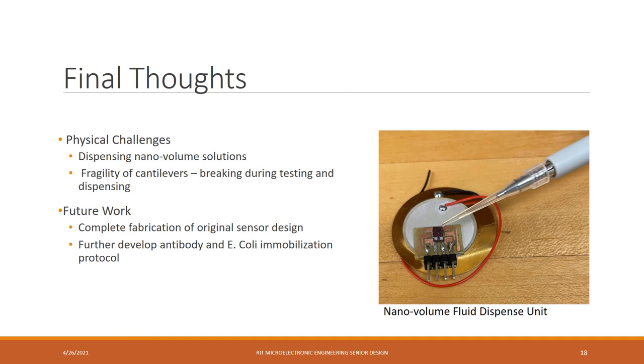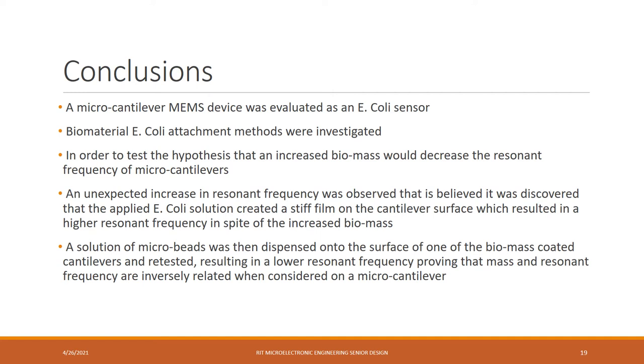Manually dispensing nano volumes of solution onto the cantilevers was difficult and resulted in a broken cantilever. Next steps are to finish processing the original cantilevers and to develop a protocol for E. coli binding using antibodies to increase the surface density. To conclude, a MEMS microcantilever device was evaluated as an E. coli sensor. The resonant frequency shifted in the opposite manner than anticipated once it was exposed to the E. coli solution. The stiff salt crystal E. coli film caused the higher resonant frequency due to a stiffer spring constant. When microbeads were dispensed on the surface, the frequency went down as expected. The theory holds true that a larger mass will result in a lower resonant frequency. With future work, it's likely that a microcantilever could be used to sense E. coli.